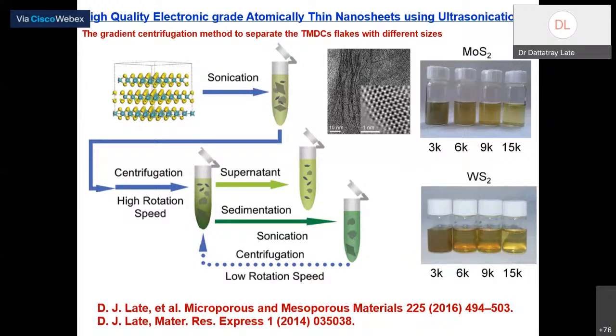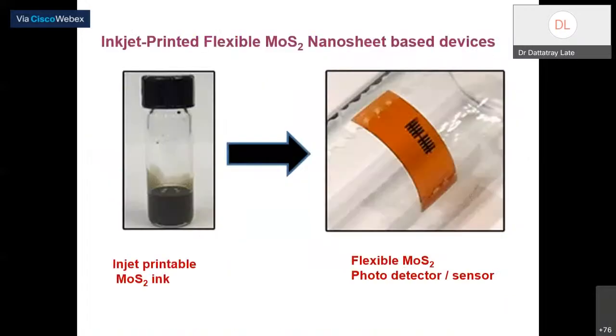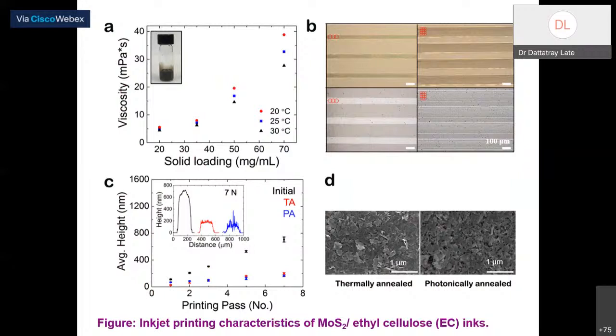Okay, once you have these materials, they are in the form of a solution, or we call this an electronic ink, electronic grade ink. So you can coat this electronic grade ink, or inkjet print it. You can coat this ink on your electrode. You can directly drop cast, and then drop cast on a patterned device. And of course, traditionally here, we have used graphene as an electrode. In between these two graphene electrodes, because graphene is highly conducting, I have put this MoS2 as an ink, and done a lot of testing.